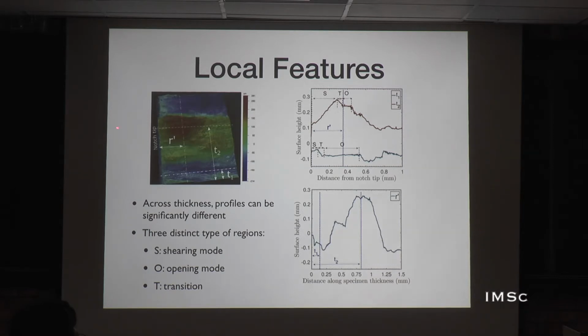Now if we go along the direction of the crack growth, which is what was reported in the first few slides where I mentioned microstructural examination, we do see a slip plane crack type of surface. But we also see some flat regions which we feel are opening stress dominated fatigue damage growth. If we look at another plane with a similar orientation, cut perpendicular to the surface, and look at the height profile, we see that this slip plane is not necessarily always oriented upward. It is also going downward, and it does not necessarily extend up to the full length always. There are flat regions which could be quite large as well.